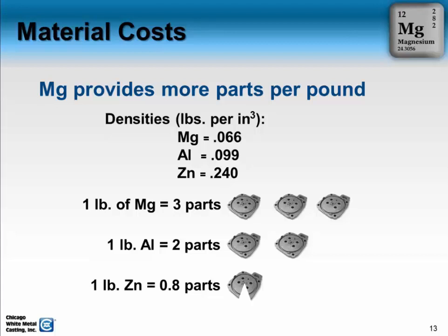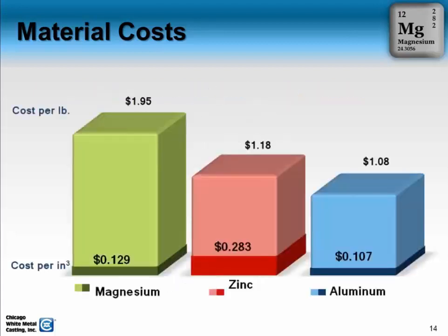So out of 1 pound of mag, you can get about 3 parts. 1 pound of aluminum, you get 2 parts, and 1 pound of zinc, you can get under 1 part, so about 0.8 parts. And this comes in a little clearer here in the next slide. But density is the other big factor into how the economics play out. So look at this slide a little bit, and this is showing a different way to represent how the density plays into material costs.